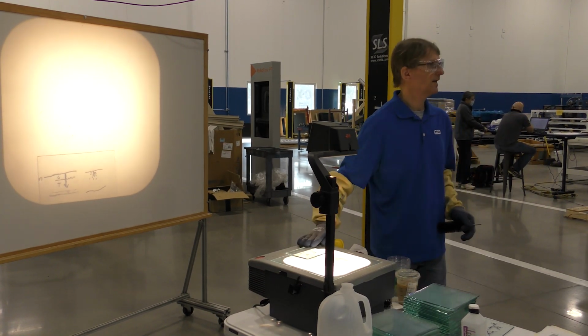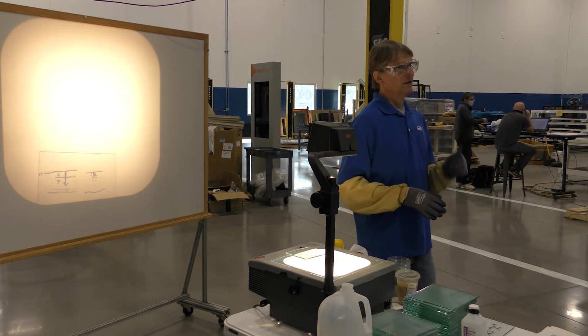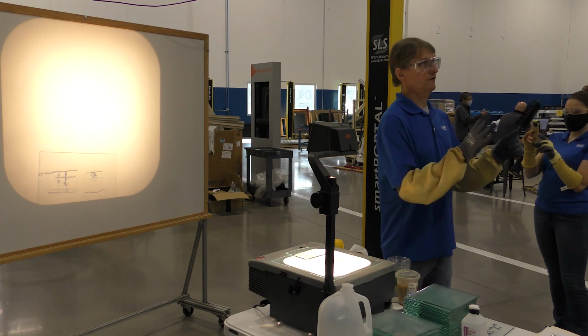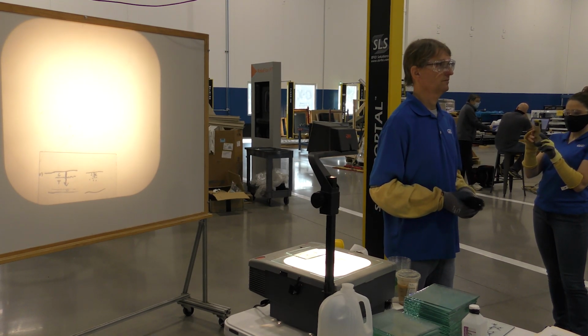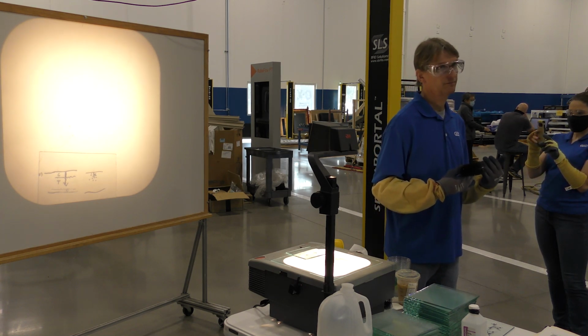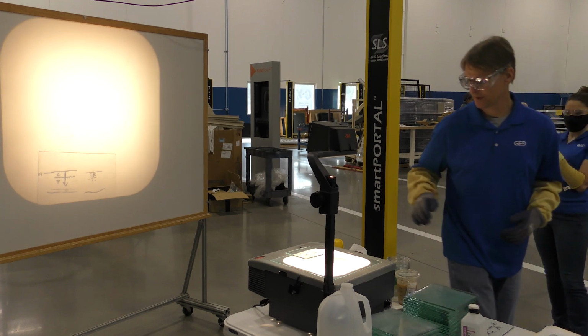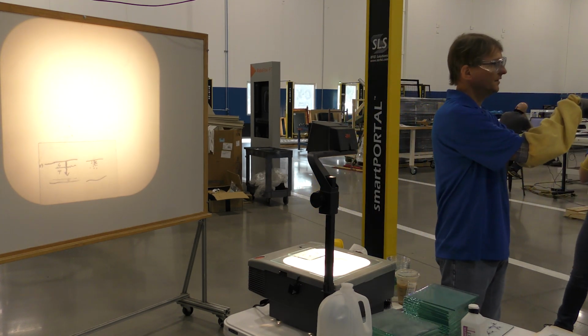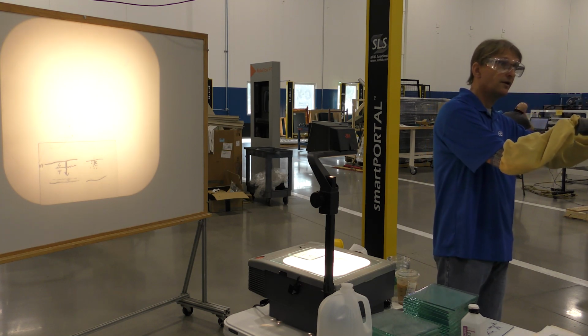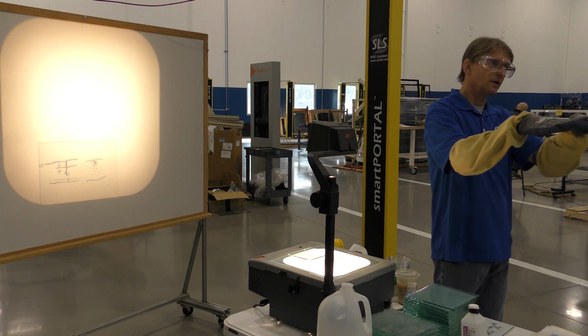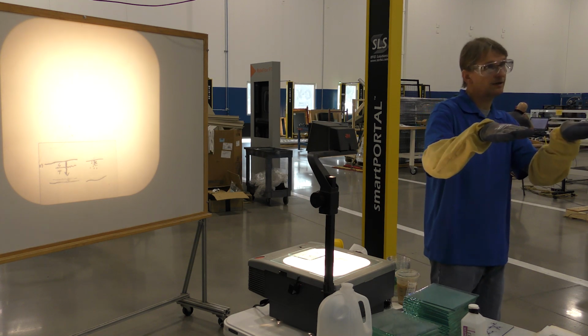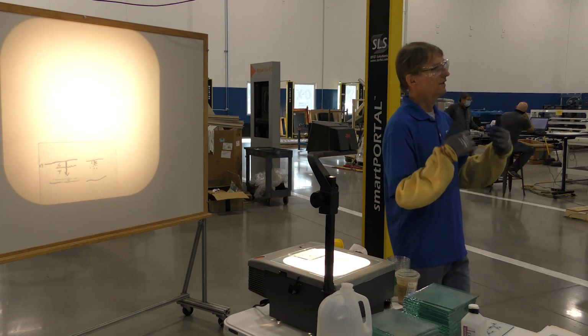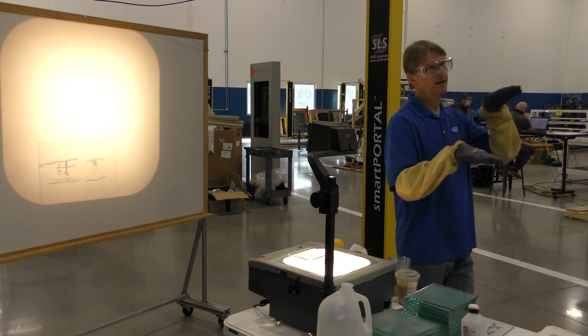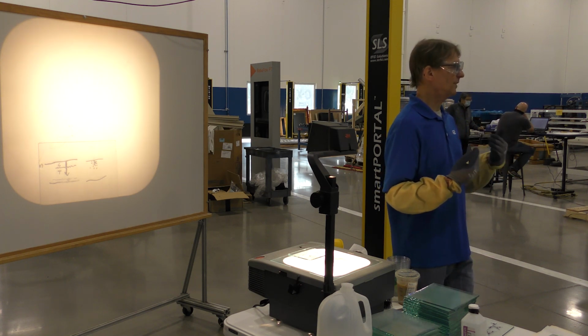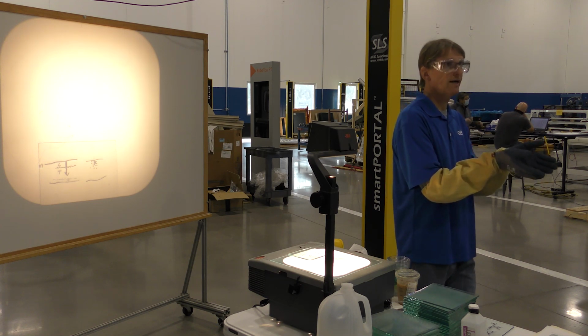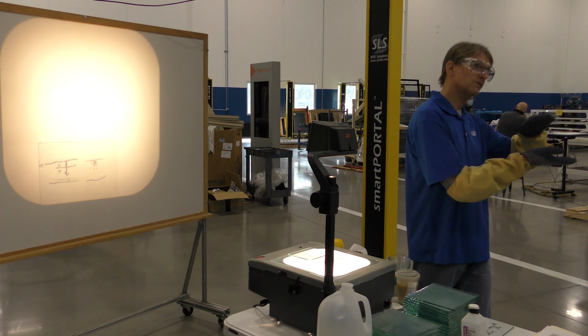Let me just explain how glass is scored and broken. Glass will almost never break under compression. Glass will always break under tension. When glass is made, you could probably YouTube it, glass going in the ribbon is red hot, molten. It goes through the float line, through the annealing, the cooling. And as glass cools, it makes a compressive shell on the outside. It's like how metal is heat treated: you bring it to orange hot, then quench it, and it makes the outside casing hard.